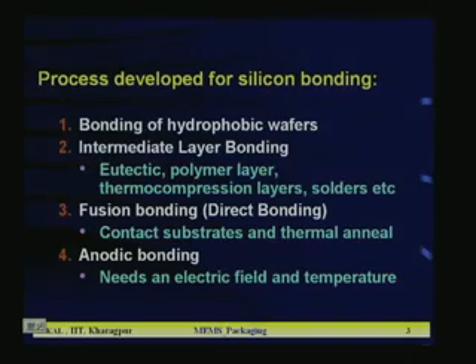In this particular area we normally use 3 to 4 kinds of bonding mechanism. First one is bonding of hydrophobic wafers, second is intermediate layer bonding, and in intermediate layer bonding several techniques are there, namely eutectic bonding; a polymer layer is sometimes used for bonding between the two layers, that is, photoresist is also used where you do not need very hard bonding, for soft bonding you can make use of photoresist. Thermocompression bonding means you have to press in the presence of high temperature. And solders: in some cases you can just use some solder materials to bond the wafer with some other package or housing.